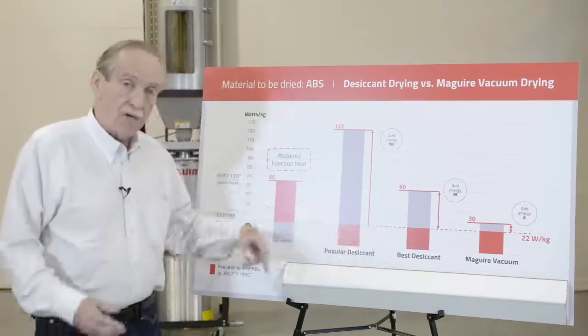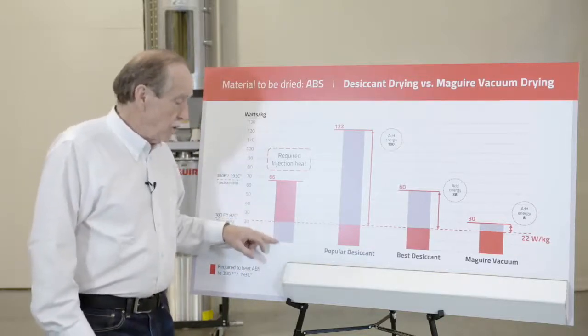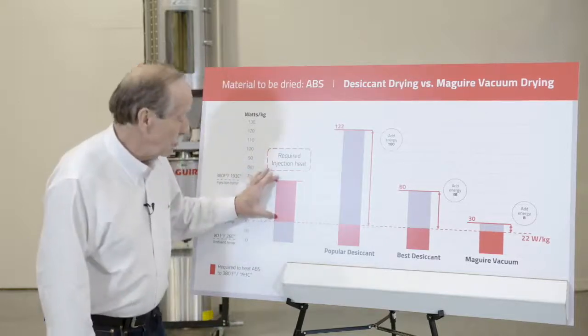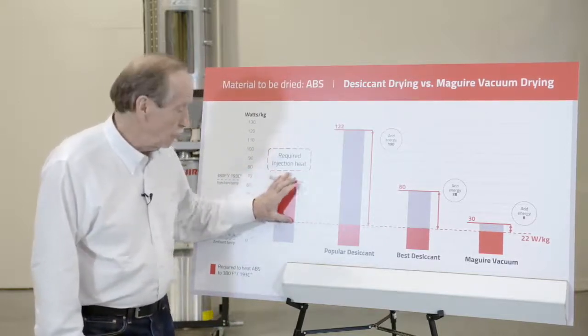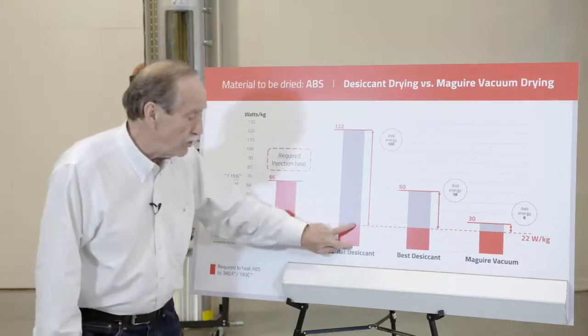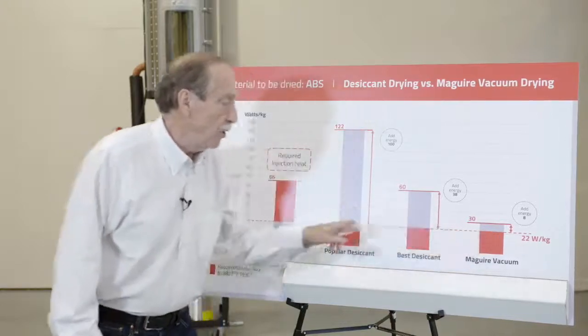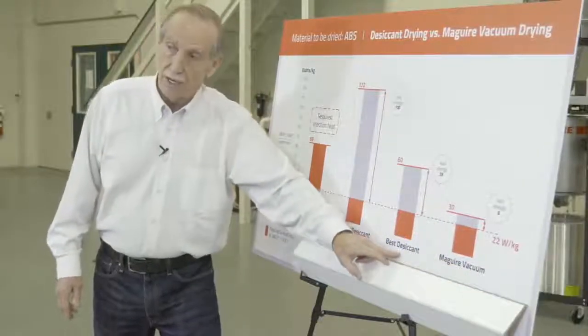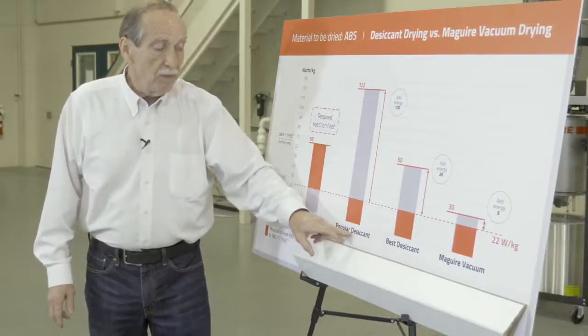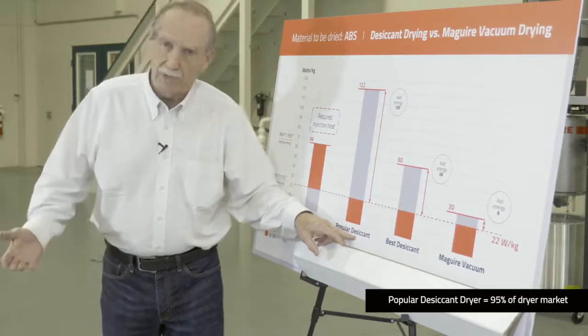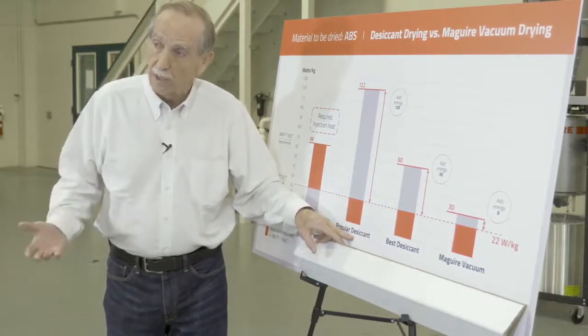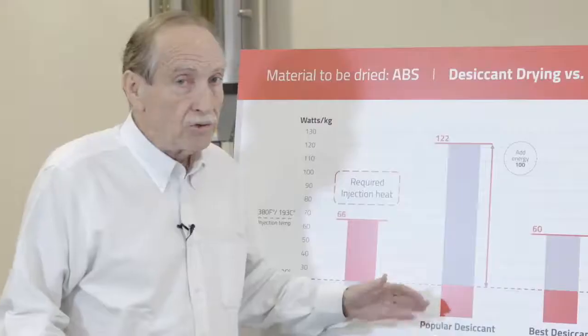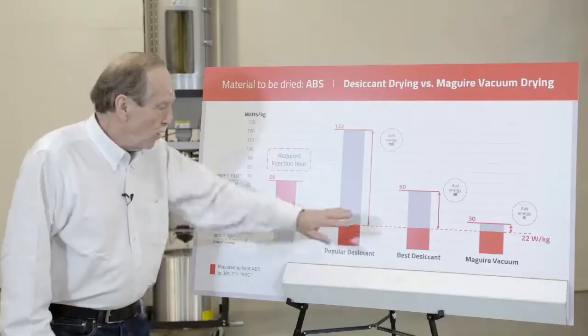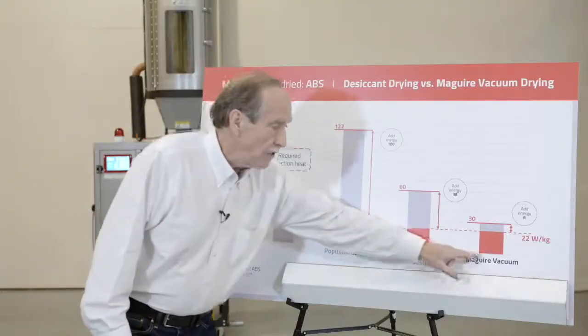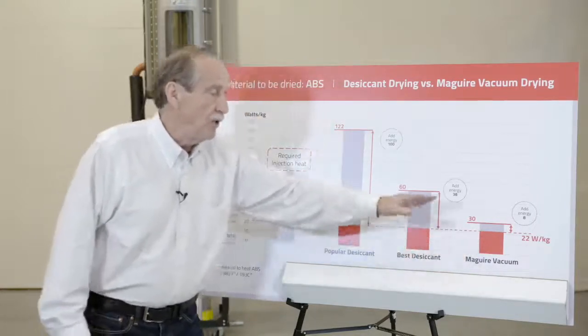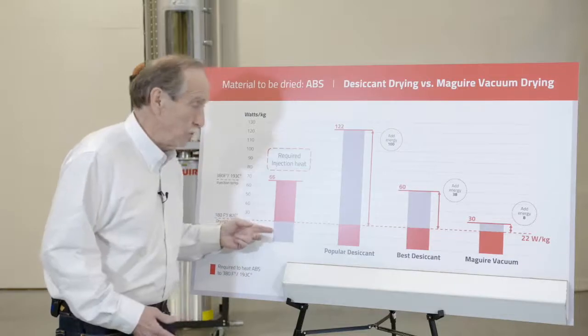Every dryer does that. That's actually all saved energy, because this section means your injection molding machine doesn't have to do that. So your injection molding machine has to provide this much energy to get it up to molding temperature, but your dryer already preconditions it by putting in this much energy. Now, the three bars are vacuum dryer, the best desiccant dryer on the market that we could find, and basically popular desiccant dryers, which represent probably 95%, if not more, of the dryer market. I'm sure that if you're running a desiccant wheel dryer today, it's one of these. The point of this chart is to say every dryer has to put that much heat in there. And it's not the fault of the dryer that they have to do that. They're actually helping the injection molding machine.